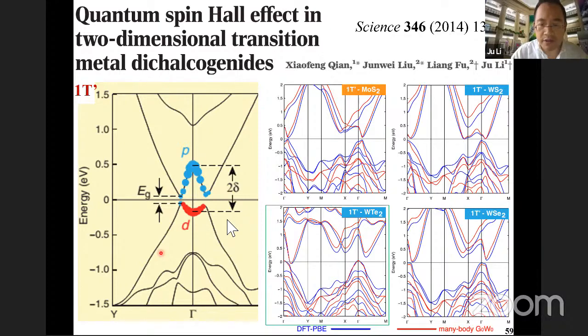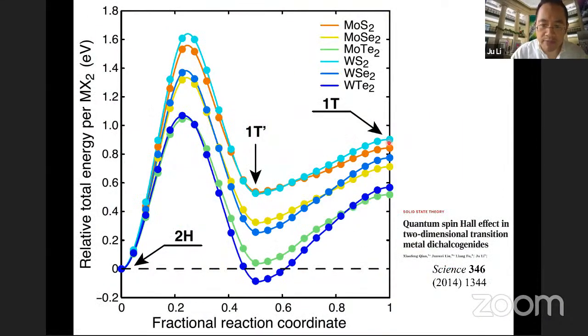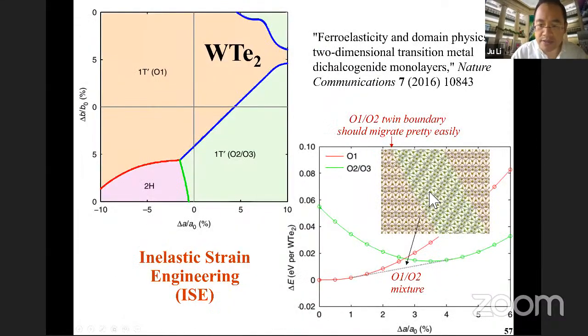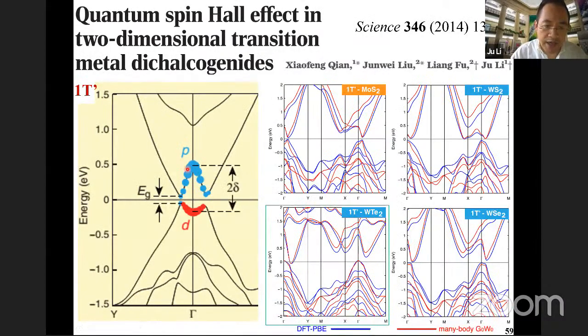However, after this T to T prime reconstruction, after this Peierls distortion, you actually tie a knot in the electronic structure where in a certain region of the wave vector space, the chalcogen P actually have a higher energy than the transition metal D. And in fact, the chalcogen would actually lose charge to the transition metal D. So that's an anomaly. And it shows up in this 1T prime tungsten ditelluride.